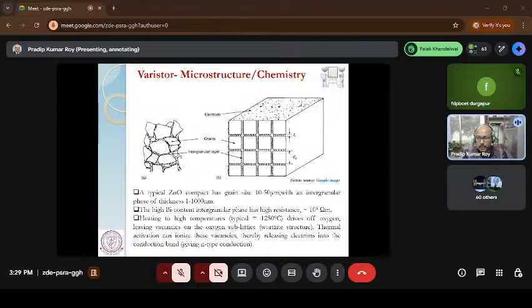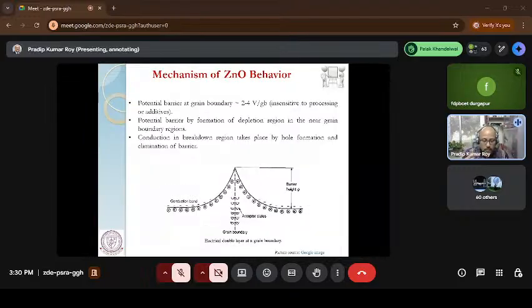If you look at the microstructure, the zinc oxide is coated with bismuth oxide. When you go for the sintering, the bismuth oxide is basically a low melting oxide, and it melts at high temperature. When it is melted, it forms a liquid phase and coats the zinc oxide grain. And during sintering, they create oxygen vacancies. These oxygen vacancies release electrons, which are negative charges, and they are deposited at the grain boundary of zinc oxide. When they are deposited at the grain boundary, they lead to a depletion layer, and this depletion layer forms on both sides of the grain boundary. So they create a Schottky barrier. Now this Schottky barrier is around 3 to 4 electron volt, and that's why no electron can flow because of this Schottky barrier. So initially it acts as an insulator.